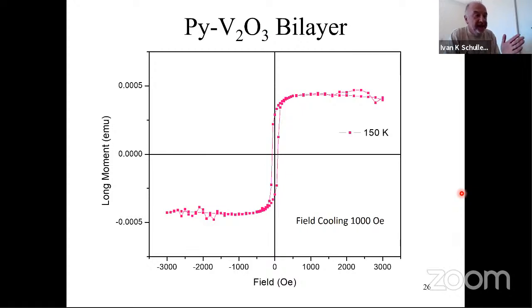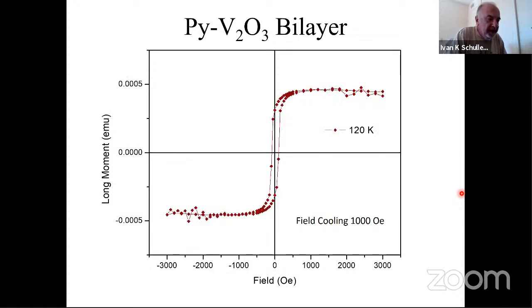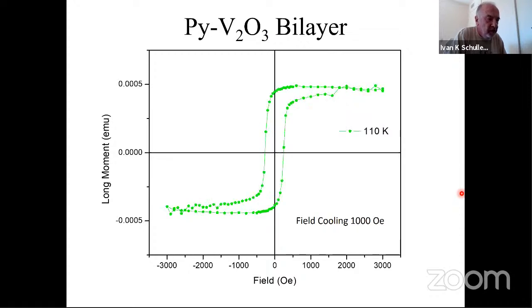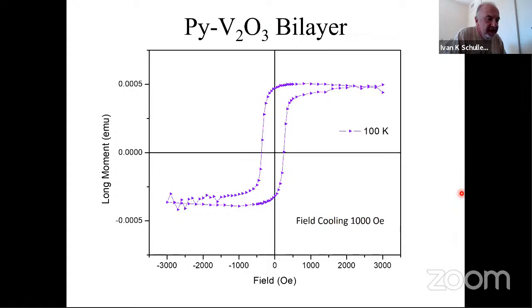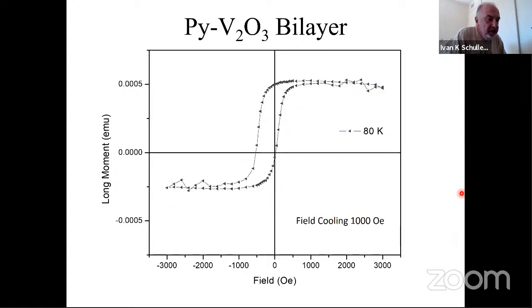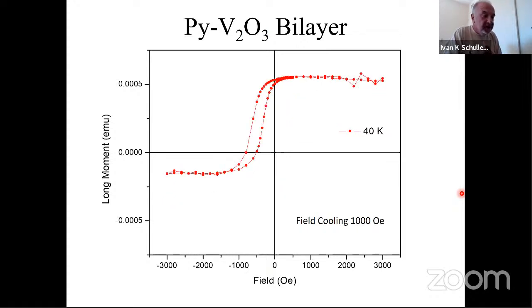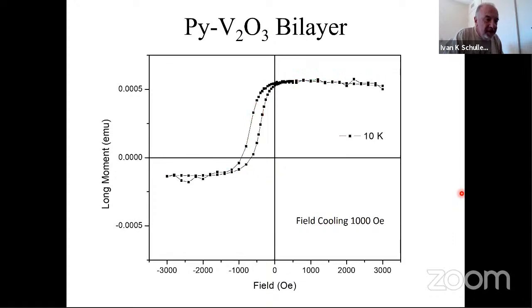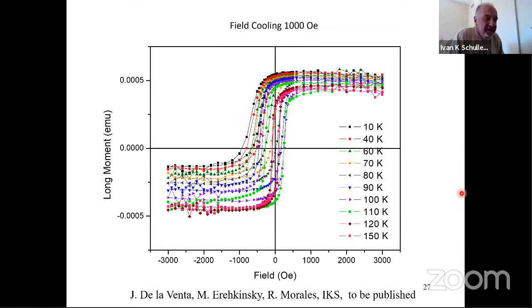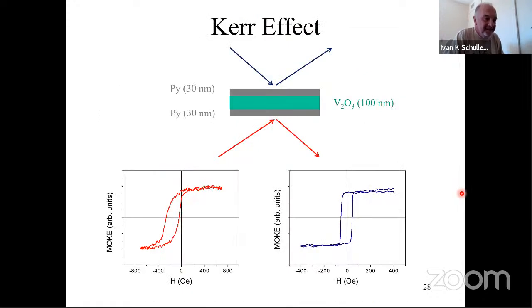And what you would expect is that as the vanadium oxide becomes antiferromagnet, the hysteresis loop switches to the right. And in fact, it does that. The hysteresis loop, as you will see, as I'm showing it to you here slowly, it switches to the right. You can see that it's moving towards the right, but it's doing something weird. It's not only switching to the right, it's switching upwards also. So what the hell is going on? This is something totally unexpected, that it switches upwards. Well, it turns out this is a red herring.